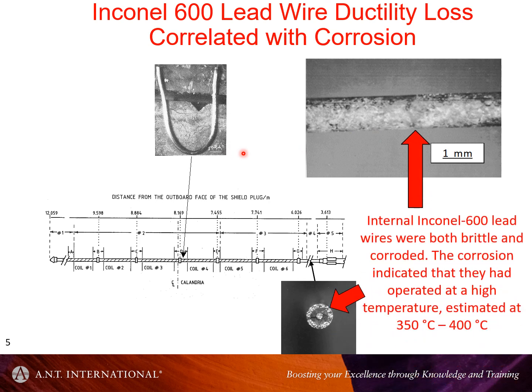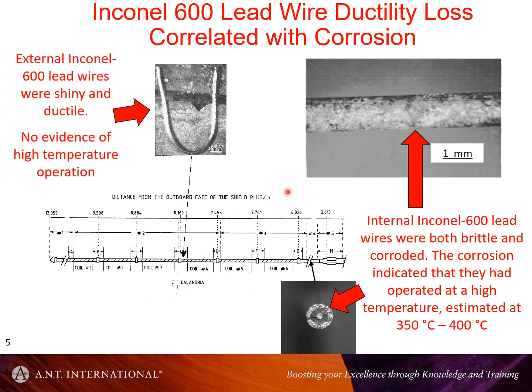And what I saw is they were very brittle in regions of the reactor where there was a lot of mass concentrated, a lot of temperature, and they corroded as well at the same time. So it turns out the corrosion layer was itself very odd. But the components which are outside of the rod, but also at the peak flux in the middle of the reactor, they were quite ductile. So it seemed like it wasn't an irradiation effect. And if it was something synergistic with temperature, clearly temperature was very dominant.